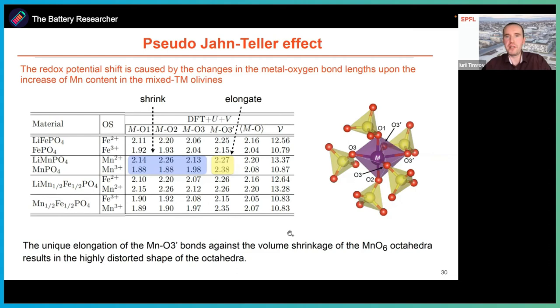It is not the standard Jahn-Teller effect because here the symmetry is preserved. The point group symmetry of the octahedron is preserved. But strictly speaking, this is not the classical Jahn-Teller effect. So it's known in literature as the pseudo-Jahn-Teller effect. And this does not occur in the case of iron, by the way.